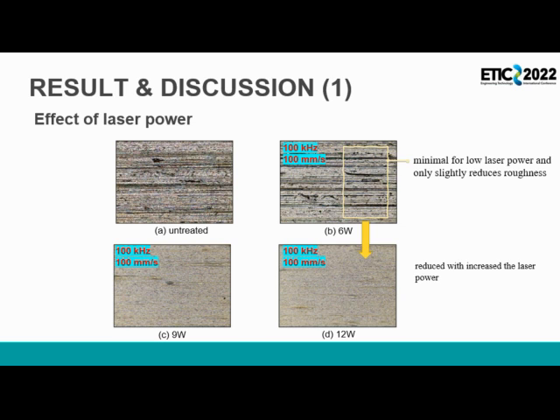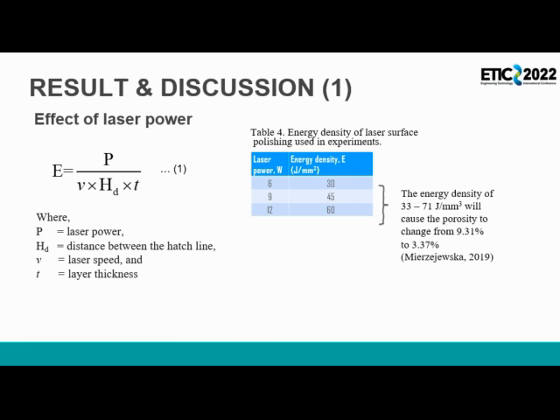In general, the two key process variables for laser polishing that have a major impact on the final surface profile are scanning velocity and average laser power. The effect of laser polishing is minimal for low laser power and only slightly reduces roughness. Roughness is significantly reduced with increased laser power. When the scanning speed is low, the roughness value can be reduced. From various previous discussions, it can be concluded that laser power is the most significant factor to reduce surface roughness.